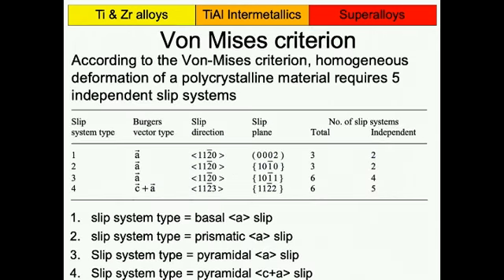Let's just look at this here. So here you can see a list of the typical slip modes in an HCP, and that's true for titanium and zirconium. So you have slip on here, the prismatic plane and the basal plane, as you can see, but the slip direction is actually the same. There's also often argued that there's a third A-type. So this is called A-type slip because the Burgers vector is a pure A component. And you can see it's a pure A component because the last number here is 0.